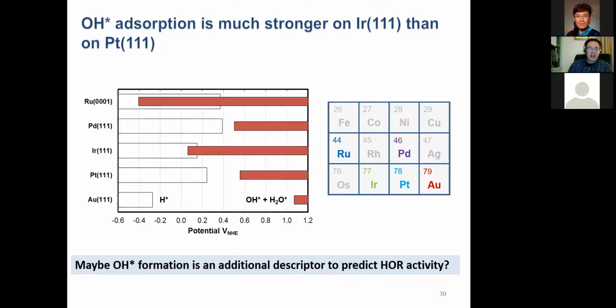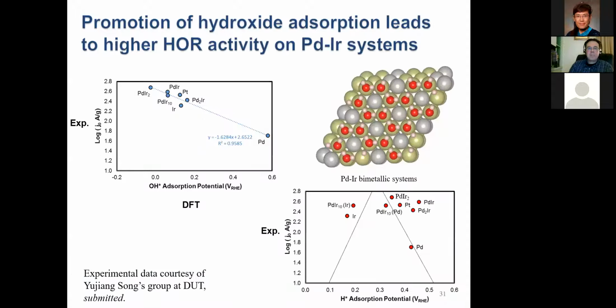So maybe hydroxide adsorption actually is another descriptor, another predictor of how fast the catalyst is going to be for the hydrogen oxidation reaction or the hydrogen evolution reaction. So we used that. We worked with Yujiang Song's group at Dalian. He varied the amount of iridium in palladium-iridium alloys and was able to get a catalyst that was faster than pure palladium or pure platinum if he had the right ratio of palladium and iridium.